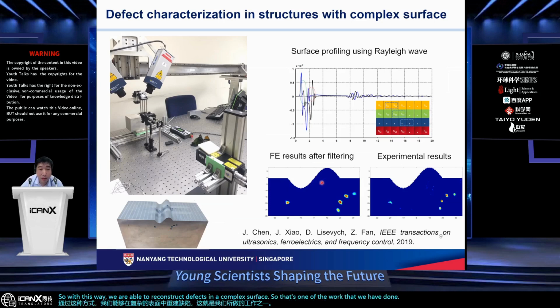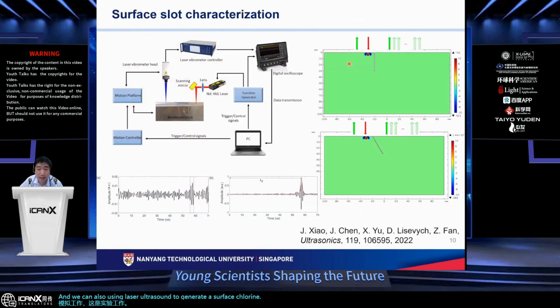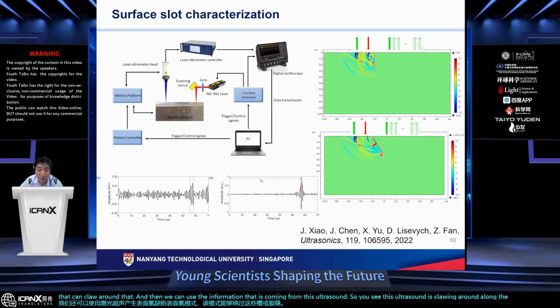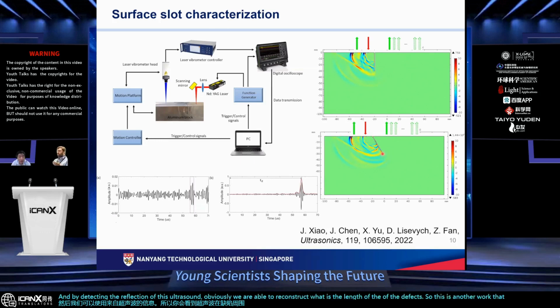This is the simulation work, and this is the experimental work. We can also use laser ultrasound to generate a surface crawling mode. That mode will be able to crawl around those slots or cracks, and then we can use the information that is coming from this ultrasound. So you see this ultrasound is crawling along the defect, and by detecting the reflection of this ultrasound, obviously we are able to reconstruct the length of the defect. So this is another work that we have done for the surface slot characterization.